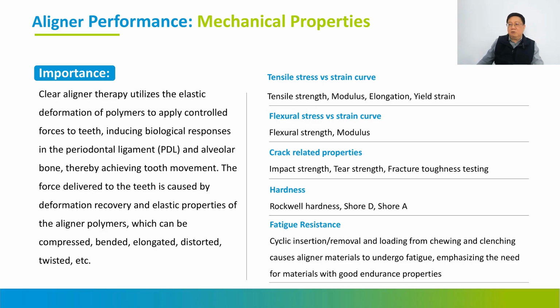I would say that Shore A 70 will be something like Shore D 20, then Shore A, let's say 80, maybe something like Shore D 30, because the metal angle touching the plastics is sometimes very sharp like Shore D, and sometimes a more dull surface like Shore A. So right now for a liner, they are measured based on Shore D, and Rockwell hardness is even higher. For polyurethane, they use Rockwell hardness as the measurement.